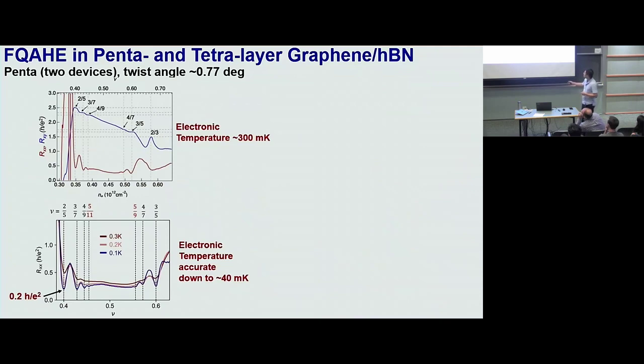And what you can see by comparing the data back then and now is that for these fractions that we have identified previously, the Rxx goes deeper. Okay, it's not 0 yet, but as temperature goes down, the dip gets deeper. The smallest residue we have now is like 0.2 h over e squared, about 1 order of magnitude smaller than the value of Rxy. Okay, and because we're at lower temperature, we actually can identify a couple more fractions like 5/11 and 5/9.